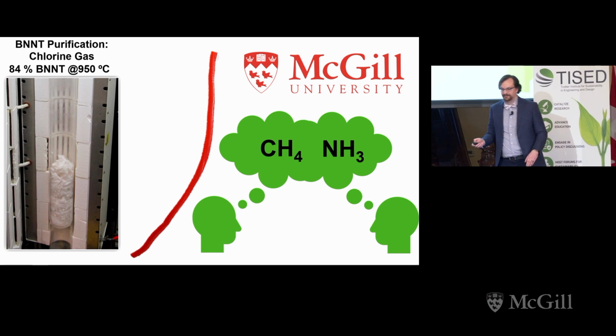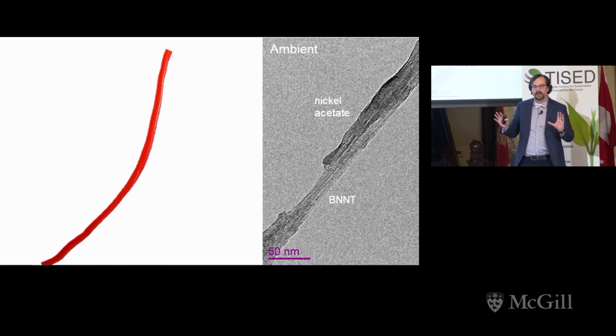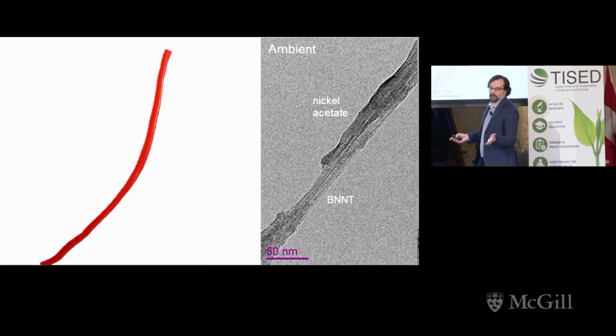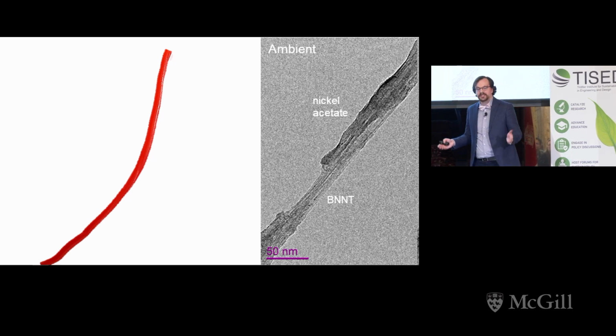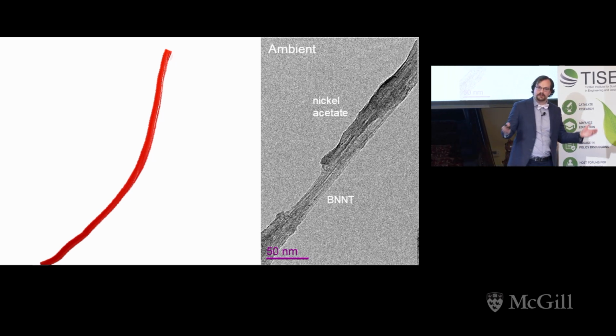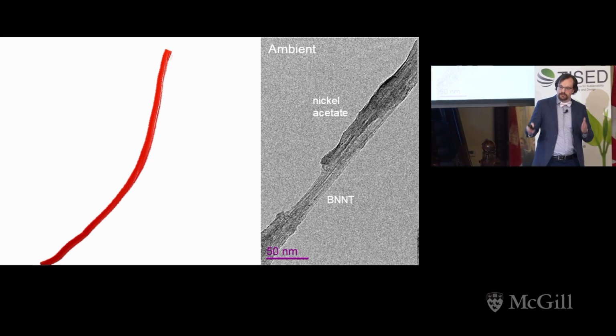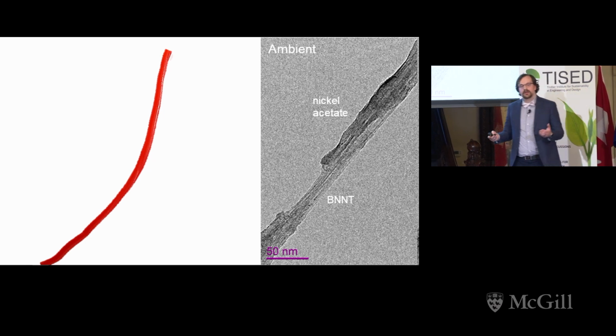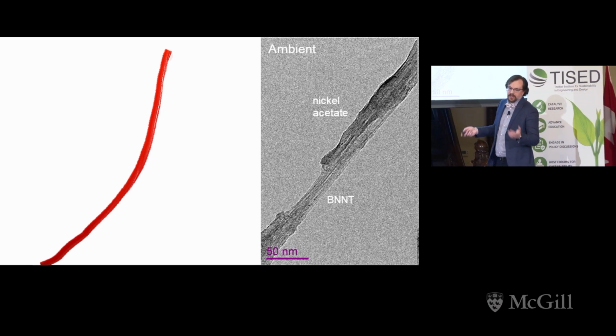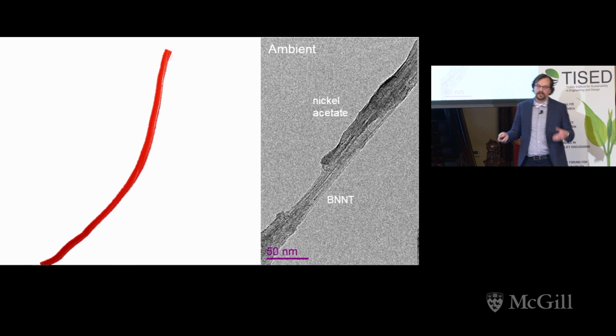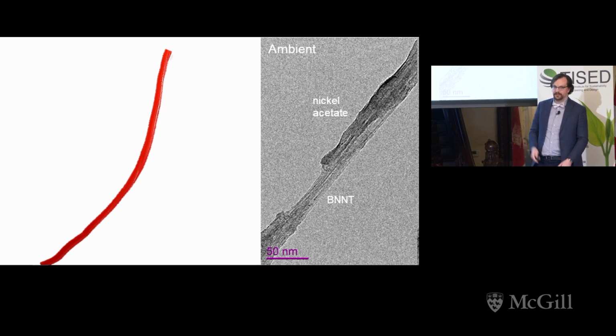So they hired me. Now, the first thing I needed to do, with my nice purified boron nitride nanotubes, was make sure I could get the nickel nanoparticles onto them. Using an electron microscope, we were able to drop cast some of our nickel precursor, nickel acetate, and start raising the temperature.